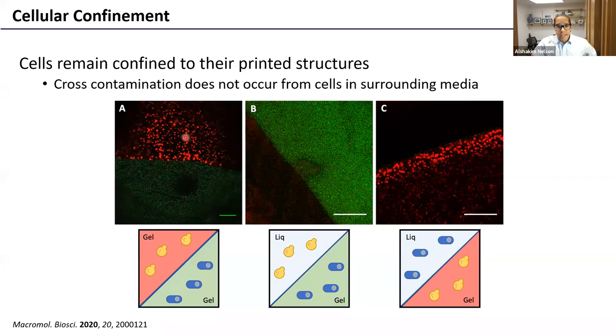Similarly, if we look at the gel-liquid boundary, I should note that over time, we do observe cells escape the gel into liquid media. So if we have a liquid media that contains red fluorescent yeast and a green fluorescent E. coli gel, then the E. coli in the gel will escape into the liquid after a period of a couple of days.